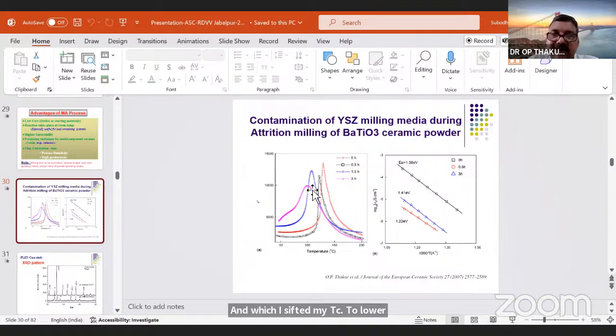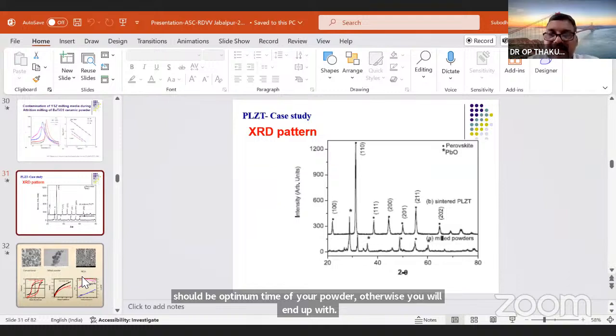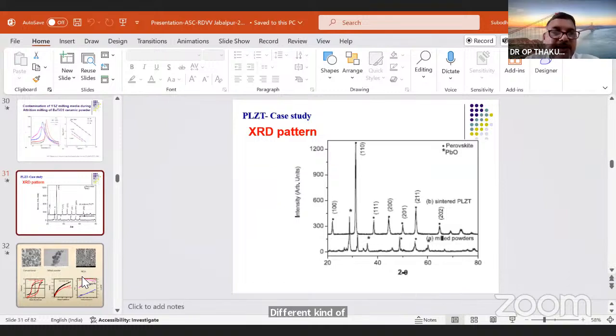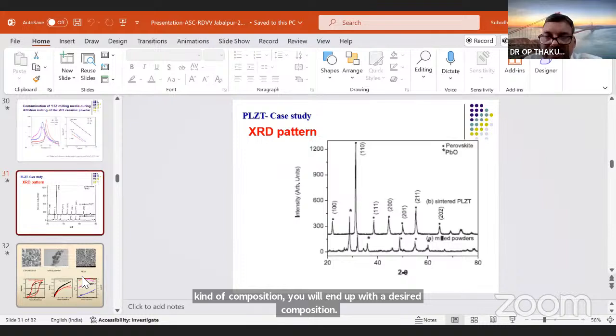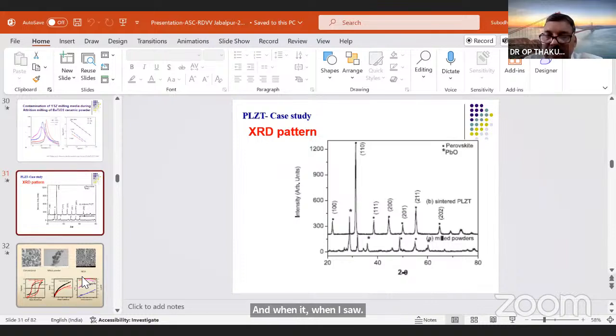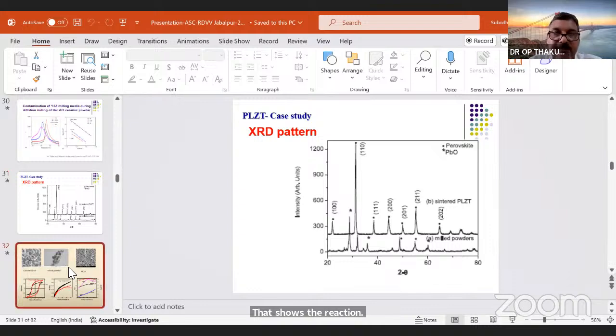So the caution from this study is that there should be an optimum time for the grinding of your powder. Otherwise, you will end up with a different kind of composition. You will not end up with the desired composition. And when I saw the XRD pattern for the milled powder for PLZT and the sintered powder, you may find that a partial reaction started between the starting chemicals. That's why peaks are appearing. That shows the reaction got started at room temperature while ball milling.